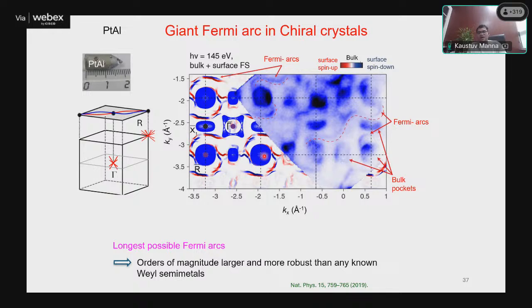It is starting from the gamma point and it goes all the way to the R point, because this is a cubic compound. So the Brillouin zone is also cubic in nature. So zone center to zone edge on the surface, it is connected with respect to the Fermi arc. Now, if you want to have Chern number plus minus 4, the Fermi arc also would be 4 number. So you must have splitting of this Fermi arc.